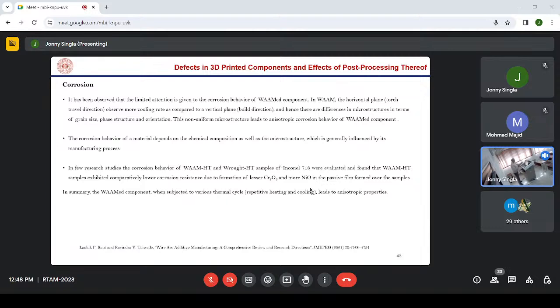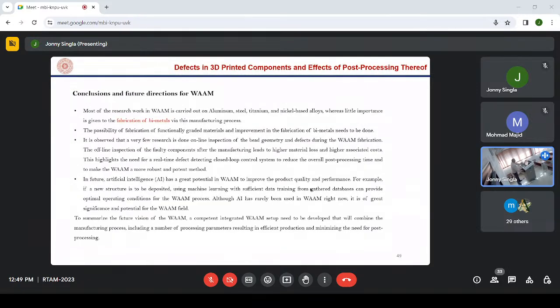If you take proper care of your process of manufacturing through WAAM, the torch speed, the scan speed, the wire feed rate, then you can control the microstructure of the material. And if you are able to control the microstructure, the associated mechanical properties are bound to improve, right? So the only thing is you should, through trial experiment, first of all establish these parameters and then you should manufacture it. Now these are some of the conclusions and future openings for WAAM.